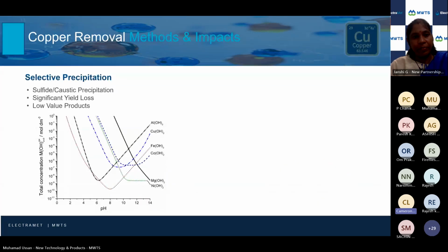Next slide, please. So we're going to look at a little bit of the existing methods and dive into why they might work for the mining industry, but not for this. Except for copper, the standard process is chemical precipitation. I'm showing here a solubility curve of the different metals versus pH, because adding sodium hydroxide and doing metal hydroxide precipitation works very well for environmental compliance on a lot of wastewater. The problem is, as you can see, every metal here is going to come out.